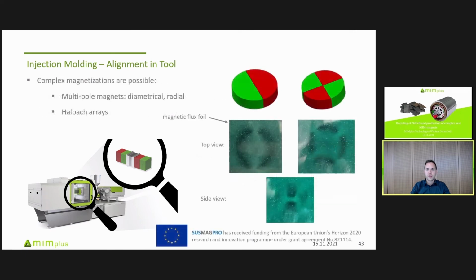A second point, which is quite interesting in the alignment and which is innovative for production of MIM magnets, is that we can realize multipole magnets like diametrical and radial magnets during injection molding. Even Halbach arrays can be produced. Here are shown two examples of a multipole magnet. We see here the green part shown with a magnetic flux foil. You see here one pole, here the second pole. Here it's a 4-pole magnet, 1, 2, 3, 4 different poles. And on the side, you also see the magnetic poles of the produced green part.